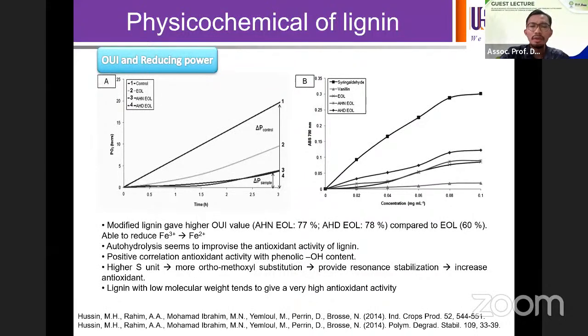So the correlation that we found was that if we modify the structure of lignin, we obtain slightly more aromaticity. More aromaticity can help improve the antioxidant activity by providing more resonance stability, and this will give an increase in antioxidant activity. And other than that, we also did molecular quantification, using GPC to check the molecular weight and also DSC to check the glass transition values. So obviously the modification of lignin provides us with a lower size, a lower molecular weight of lignin, which can also contribute to the antioxidant activity.